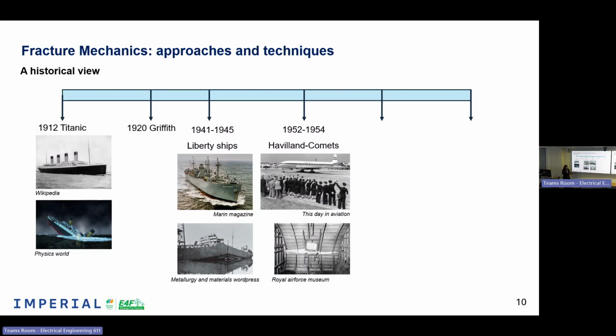And it was, in the moment, a very important news for the world, but some of these kind of aircraft, they were crashed, and they were normally crashed after about 3,000 hours of flight. And when they tried to see what was happening, they observed these kind of cracks that were generated around the windows. Why? Because there were stress concentrators, and these stress concentrators were generating fatigue cracks. So now we don't have stress concentrators in the wings, in the aircraft, in the windows. You can see that this has a round shape. So this was also pushing science to really understand what was happening.